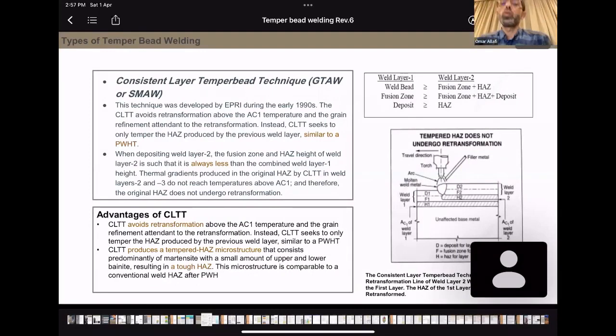Another technique was developed, which is the consistent layer temper bead technique using automated GTAW or manual SMAW. So the good thing in this technique is that it doesn't take the base metal temperature above the lower critical temperature, which is AC1. So it is something similar to PWHT. It can restore the mechanical properties of the base metal, similar to PWHT. But as we can see here,